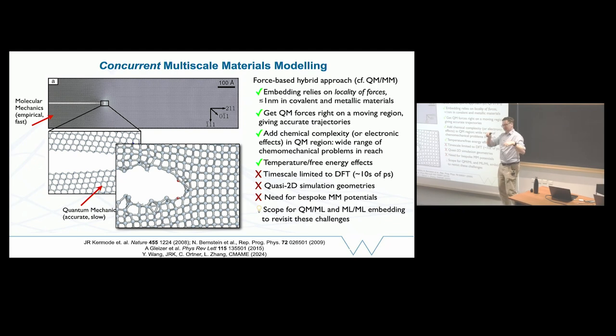But we have to wait ages for the next molecule to get there and so on. So it's not really possible to study the whole process with DFT like this. We're using pretty simplified simulation geometries. These things are narrow in the direction, in the plane, into the screen. That's just to keep the cost under control. I can afford a few hundred atoms at DFT level, not more. And actually, one real challenge when I was doing this a few years ago is every time you move to a new system, you need a new embedding potential for the outside. It takes you ages to set that up. So this is, again, somewhere where machine learning can really help, because if we have already a good quantum mechanical description of some region here, we can fit a model to that and very quickly get an embedding potential.